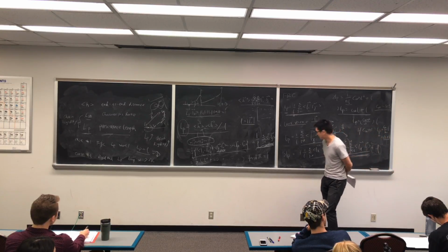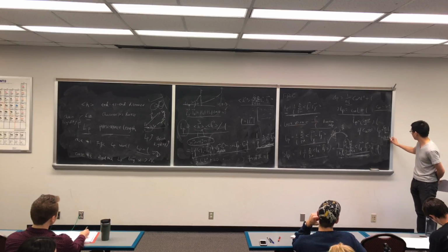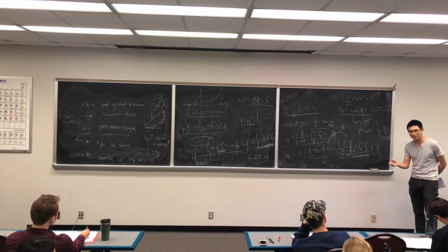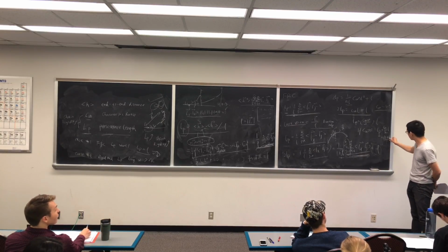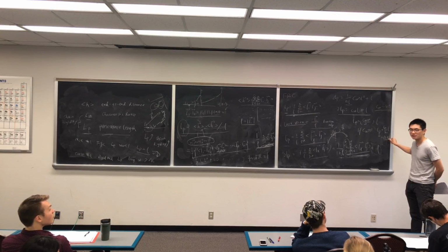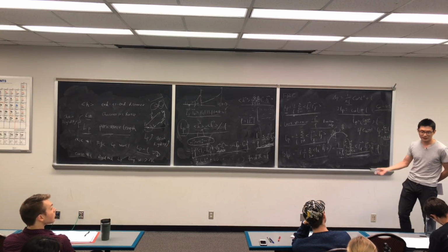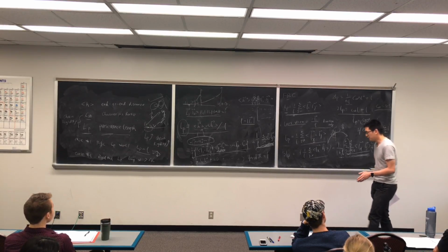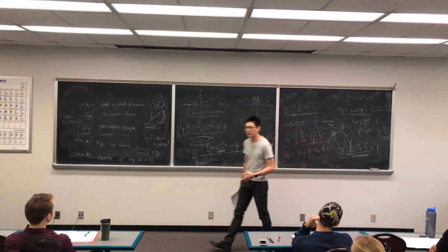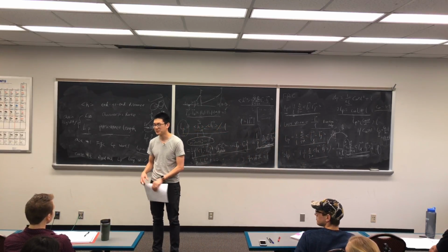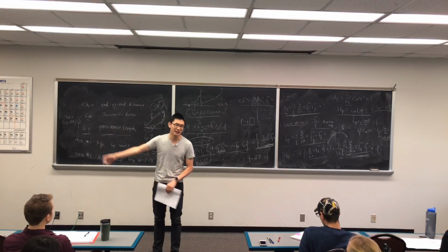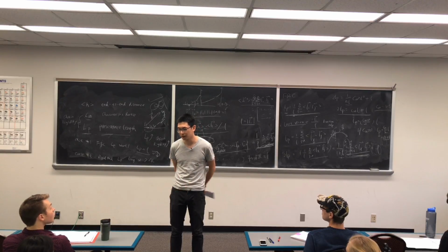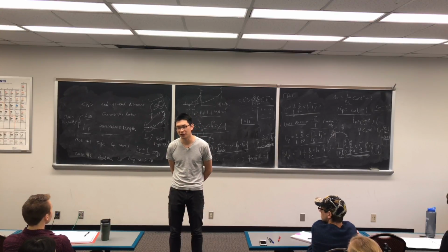Let me give you some numbers. L, we know the carbon-carbon bond is about 1.5 angstrom, right? So persistence length in this particular case is definitely less than 1 nanometer. In other words, in a very common, relatively soft polymer, after 1 nanometer your chain has already lost direction. It doesn't remember the direction of the several bonds before it. So it's relatively soft and coiled.